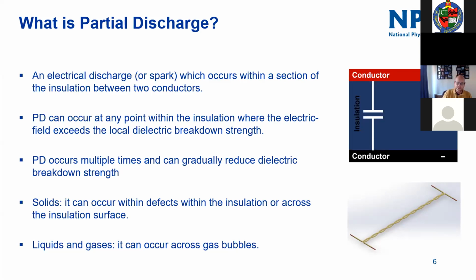It occurs in solids. It's really quite dependent on the sort of defects that you have within the dielectric, and ultimately, of course, it will occur across the surfaces of the insulation. So you don't have to just break down through the whole insulation. You can break down to a shorter distance to the surface, and then break down across the surface and back through the dielectric again. And it does occur in liquids and gases as well, within bubbles within those systems.